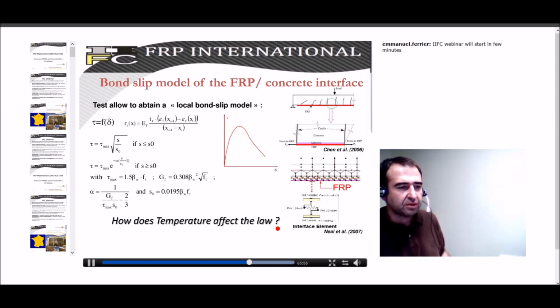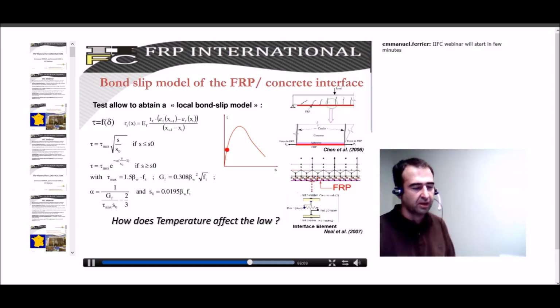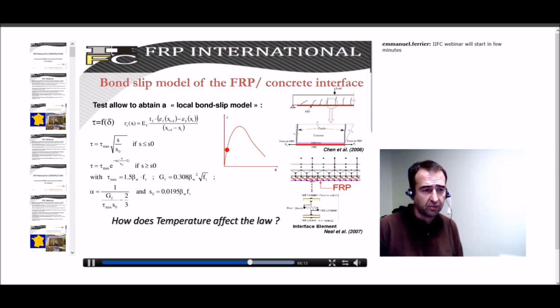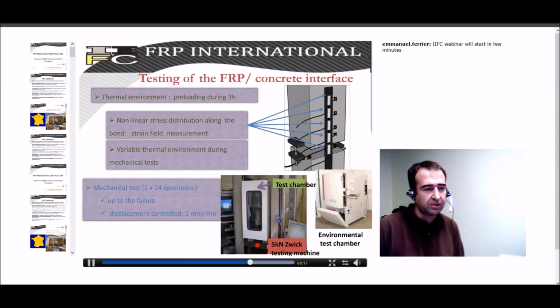So what we have done is trying to identify how temperature affects the local bond slip model I have mentioned before. I mean, are all the proposed equations I mentioned before only good at 20 Celsius, or are they good for any temperature? This study is very recent. I presented it at the CICE conference in Vancouver last summer. What we have done is combining stress and temperature in a heating chamber. We have tested about 50 samples with different temperature conditions, and we have tested 2 different FRP systems.